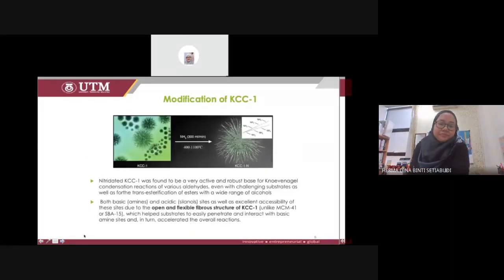And then they also modified the KCC1 with ammonia. Then they found that the nitridated KCC1 is a very active and robust base for Knoevenagel condensation reaction of various aldehydes, even with challenging substrates, as well as they also tried on the transesterification of esters with a wide range of alcohols. Why could this kind of reaction proceed with such excellent activity? This is because, as you can see here, when they zoom in on one of the fibrous structures, you can see here this is the fibrous structure, and then this is the modification of the ammonia producing the amine.